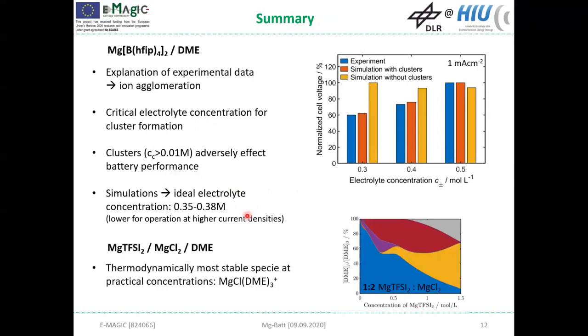Moreover, we started to analyze chloride-containing electrolytes, and we found that the most stable species in the bulk electrolyte at practical concentrations is the solvated magnesium chloride plus. So with now knowing the main species of the electrolyte, this will be the basis to have a further look at the kinetics at the electrode and to adapt our formula for magnesium kinetics to the chloride-containing electrolyte. And so we hope that with partners we can have more information about the role of the chloride in this magnesium battery.